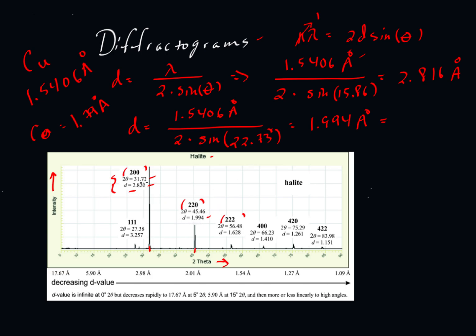Now, the last thing we want to do, besides relating these numbers, is think about the way in which these values are ordered. This is kind of like a fingerprint for halite. Halite not only has a strong peak at these particular angles corresponding to these d spacings, but notice that the biggest peak is over here and the next tallest peak is over here. The way we order them is usually by allowing the largest peak to represent a value of 100, and then the heights of all the other peaks on this intensity scale are relative to that.